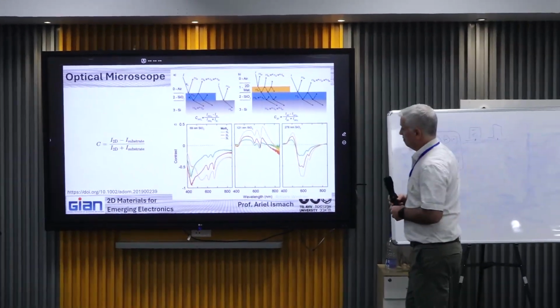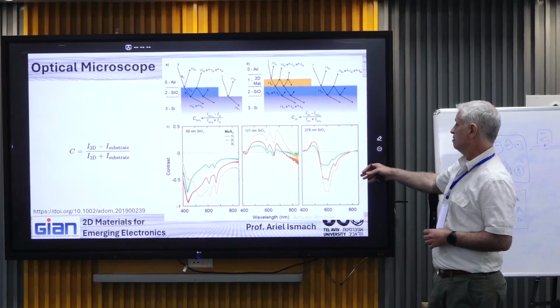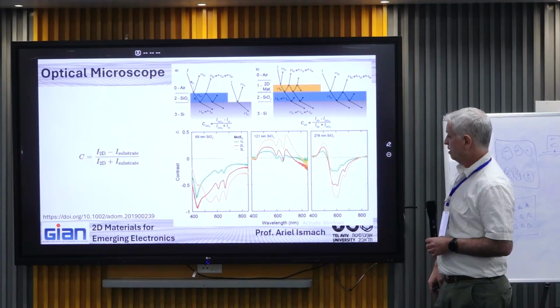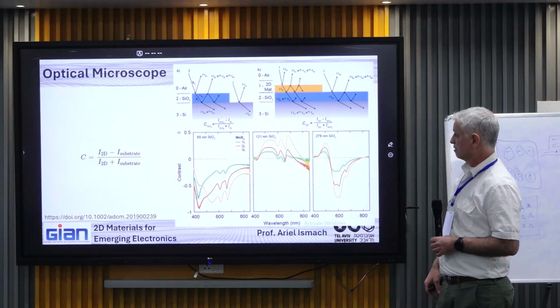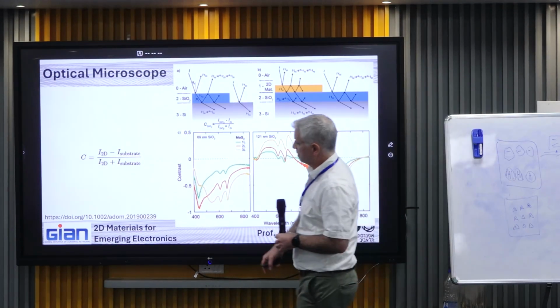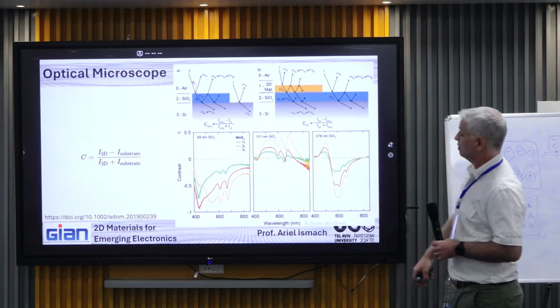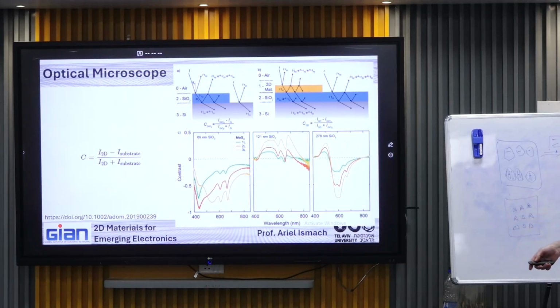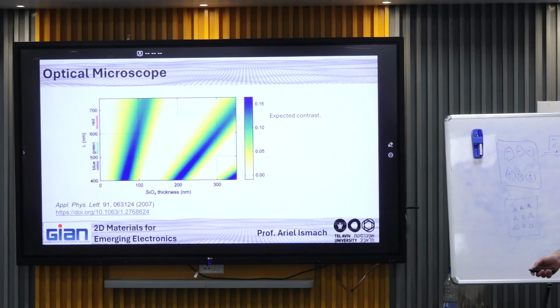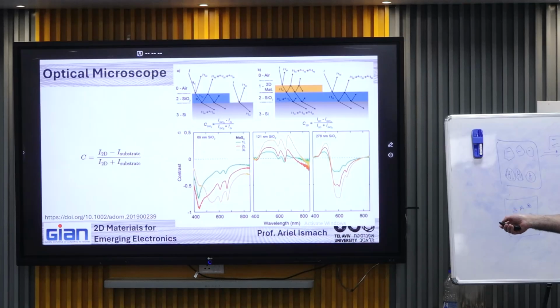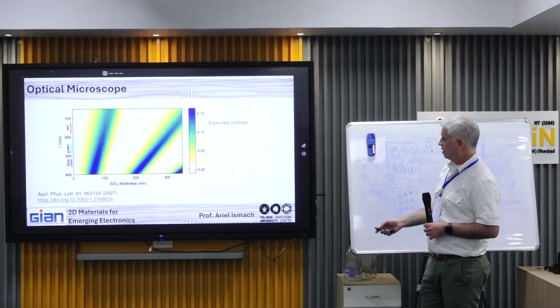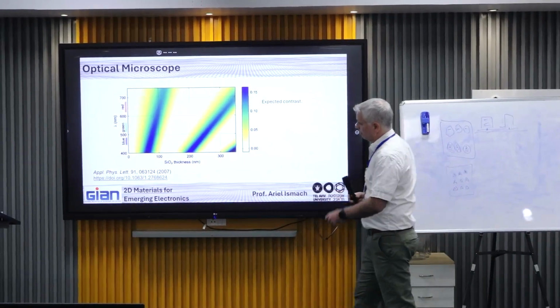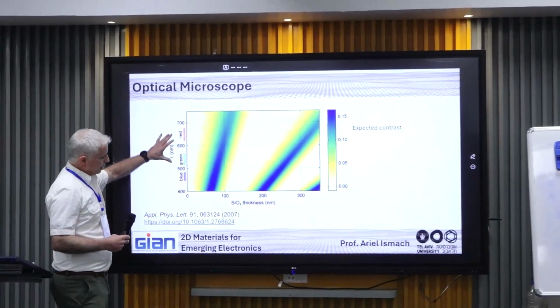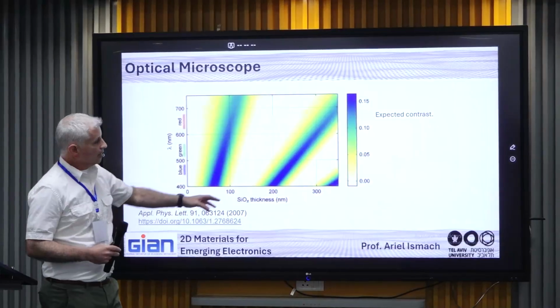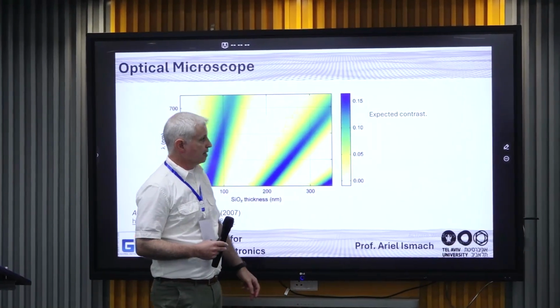If you put the sample on a different substrate, you will get completely different results. Here you can see the contrast for the different number of layers and for different thicknesses of silicon dioxide, which is a critical parameter. Here you can see the calculation for the contrast, which is the intensity coming from the 2D material minus the intensity of the substrate, divided by the sum. And then you can take a lot of measurements, different wavelengths and different thicknesses, and plot, here you can see the wavelength, of course in the visible, as a function of the silicon dioxide thickness, and on the 3D, the color is the expected contrast.